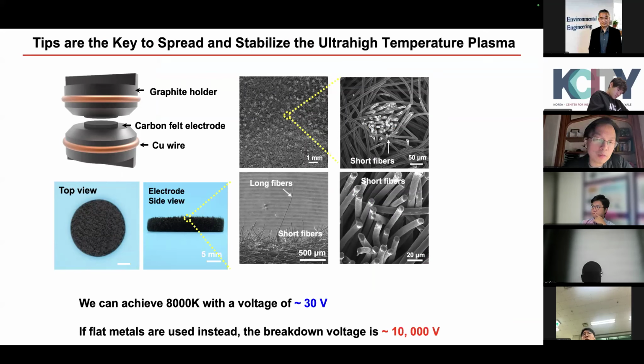We invented this about 2.5 years ago. We had a paper in Nature. What's happening here is that instead of using two metal plates, we have tips, like carbon tips, and you know where you're going to shoot an electron, you know where you're going to collect the electron. So it's very stable, relatively speaking. And then you have a lot of plasma tips, for example 10,000 tips, right? All these tips will generate plasma, and all these plasmas will basically support each other. As a result, you can have a very stable plasma.